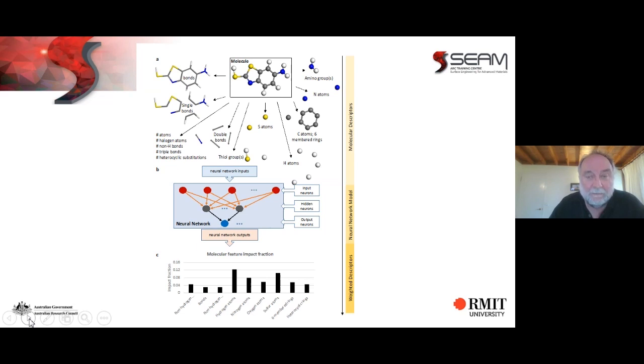So we tried to do that with the HOMO-LUMO gap and purely DFT modeled parameters, and found that it wouldn't work. From then we said, let's have a look at some of the characteristics of the molecule. And we used a program called SMILES to pull out a large number of features of molecules. We ran this through the neural network against the electrochemical properties, and we then did come up with a good neural network generated model.